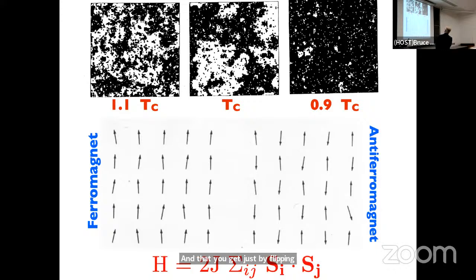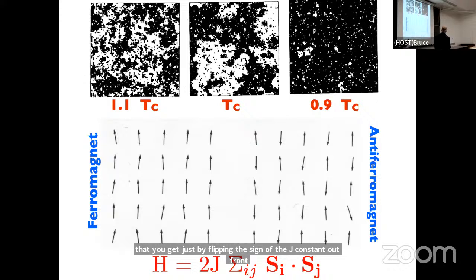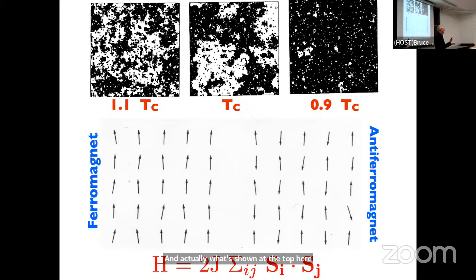What's shown at the top here is a two-dimensional real space realization of this sort of problem. These are classical Monte Carlo results. A little black square would be an up spin, and a white square would be a down spin, for example. You can see that above the phase transition, there's as much black as white, and it's not completely disordered, but it's largely disordered. There aren't correlations greater than about this sort of length scale here.